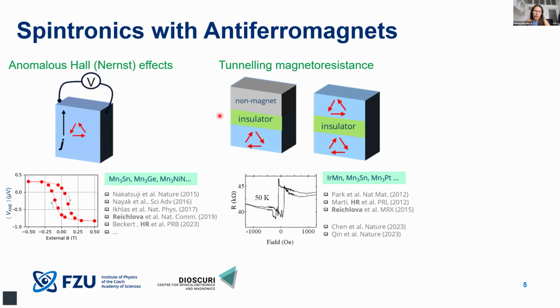insulating barrier. And here I intentionally put two cartoons to show two variants of this tunneling magnetoresistance. One of them has one layer of a magnetic material, and on the other side a non-magnetic electrode, for example, platinum. In this experimental configuration, the tunneling magnetoresistance relies on the anisotropy of the ferromagnetic, or generally magnetic, electrode below the insulator. Sometimes it's referred to as tunneling anisotropic magnetoresistance. And this effect is typically not very large, but it can in principle exist.